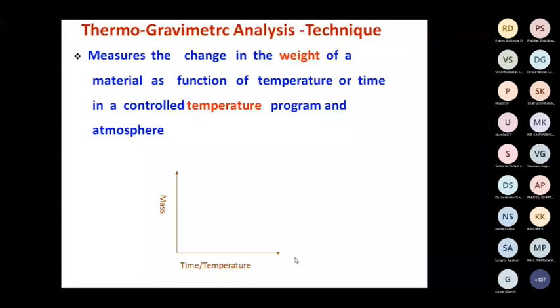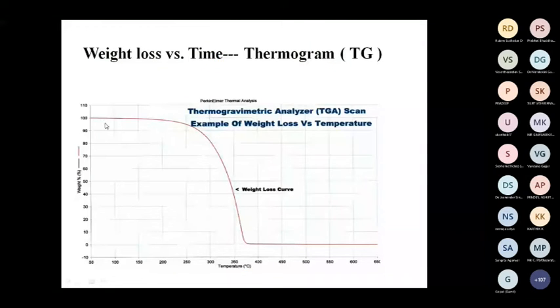You have the furnace and balance, both together. So you measure the change in weight as a function of temperature or time in the controlled heating. If you are studying mass versus time, it is called thermogravimetric analysis. While heating, the mass comes down. This is a weight curve. Weight loss versus time is called thermogram, or TG.